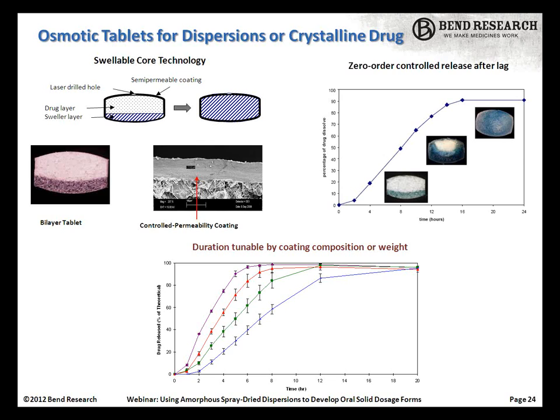It's a bilayer tablet that has a swelling layer and then a drug layer. In this case, the white or upper layer contains the drug, in this case the SDD. Generally, about 30% of that drug layer is the SDD, as a rough rule, or less. So we just apply the standard technology, the laser drill, and what you see on the right-hand side behaves as expected for this technology, where the drug hydrates and the drug is entrained,